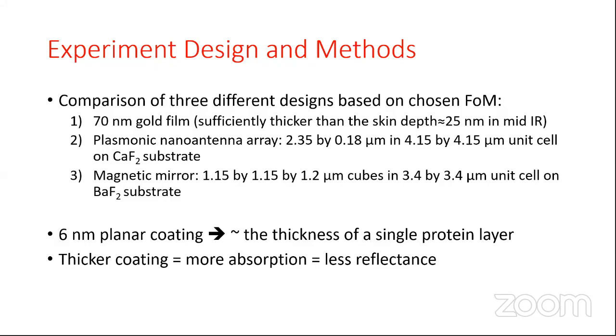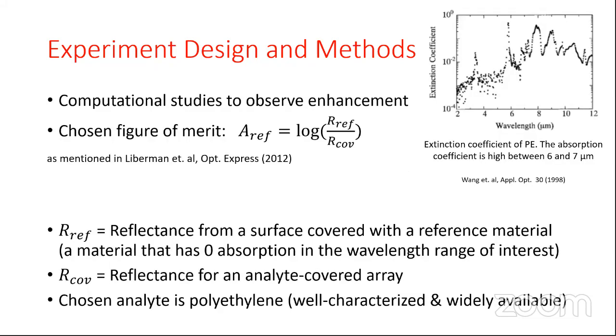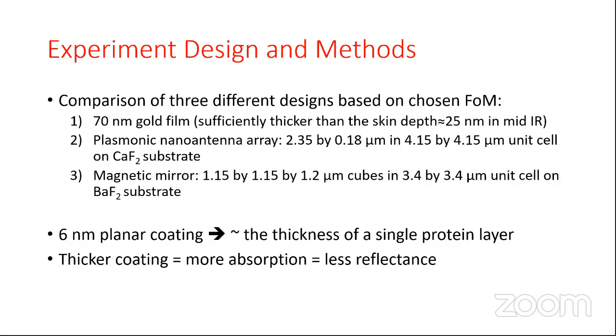Second one is a plasmonic nano antenna array. This is pretty much the state of the art, and it's a 2.35 by 0.18 micrometer rectangle of 70 nanometer thick gold in a 4.15 micrometer square unit cell. And the substrate was calcium fluoride. And this is also the same structure from the paper that I got the figure of merit from. And the magnetic mirror is 1.15 by 1.15 by 1.2 micrometer cubes made out of telluride in a 3.4 micrometer square unit cell sitting on a barium fluoride substrate.